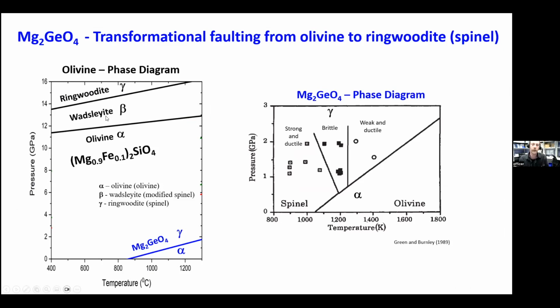So what people have done is they take analog materials. So Mg2GeO4, you replace the silicon with germanium. This lowers the pressure required to transform in the phase boundary. So now you can run an experiment at around 3 GPa and generate the transformation. And back in the late 80s, early 90s, Harry Green and Pamela Burnley did just that.